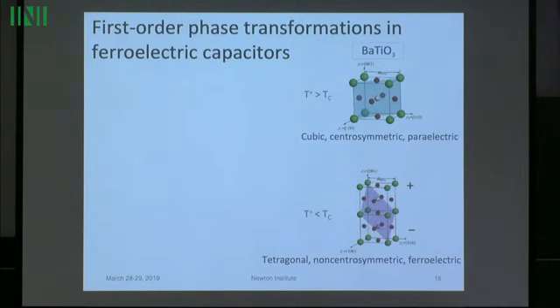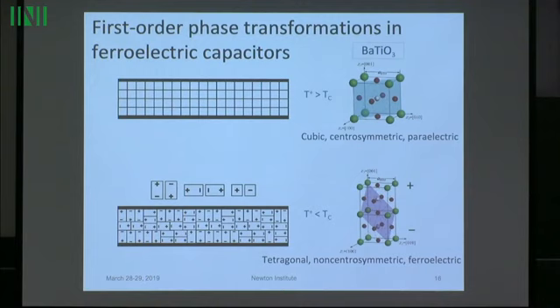They have that shape-dependent term. It's the same term. So the only main difference is that in ferroelectric materials you have free charges. Charges can move in your system, and that requires another term of the energy, which was not in the magnetic models. There are no magnetic monopoles, so there are no magnetic free charges, and so there's a certain energy which was not included in the magnetic case that needs to be included here. If you have free charges, it depends on the situation.